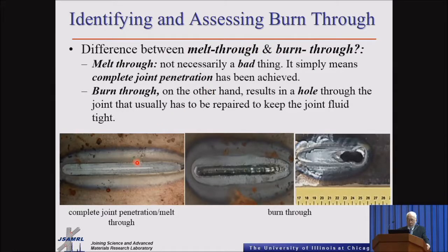So like you see right over here, you can see some kind of oxide. You might have some partial melting of the backside of the plate, but the weld is contained by the plate. In the case of the burn through, especially in the thin 5 millimeter, 4.8 millimeter plate, for us, that was a burn through. And of course, if you have a big hole, it is very obvious that you're dealing with a burn through.